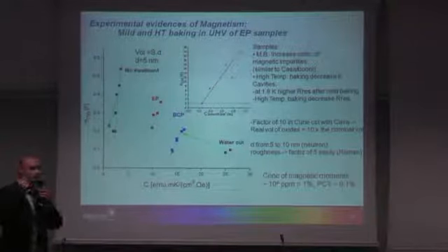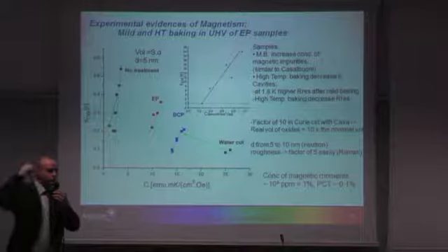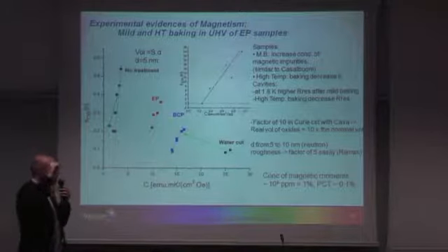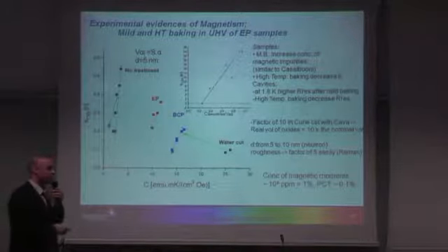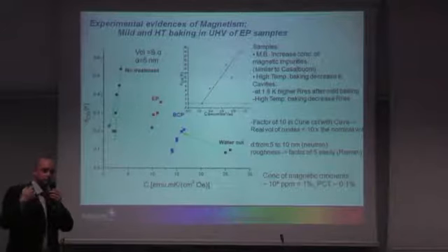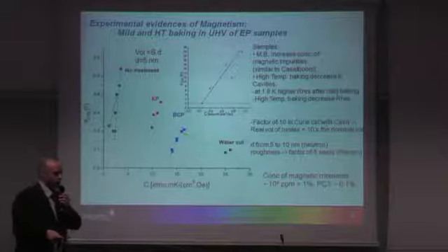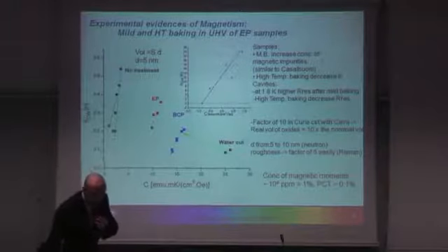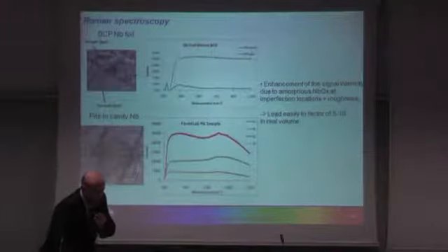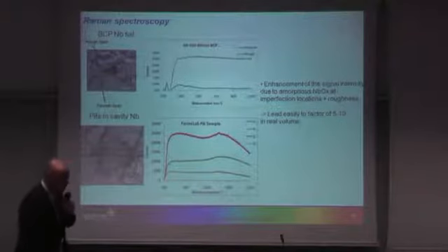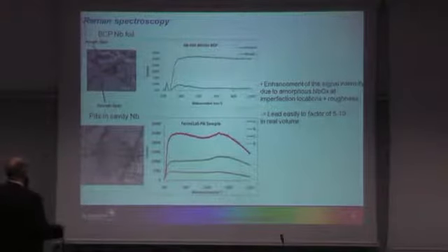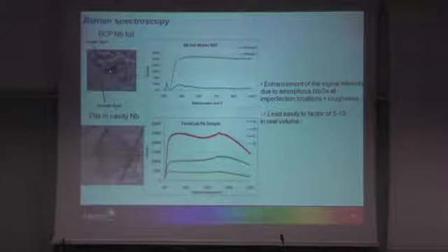Point contact is measuring the effect of magnetic impurities, which actually, the superconductor feels the magnetic impurities that are the closest to itself, which means they have to be not in the insulating outside too far from it, but right on the interface. So basically we will have fewer impurities felt by the superconductor than there really are, a factor of 10 roughly.